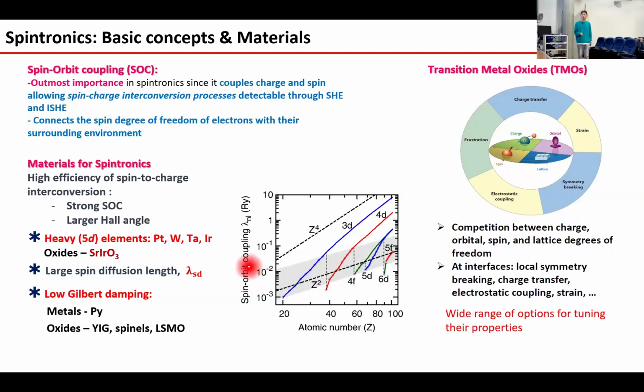In this figure, we show that the spin orbital coupling is strongly dependent on the atomic number, where the 5d elements show a relatively larger atomic number, corresponding to a relatively larger spin orbital coupling. And also another alternative is the oxides, like strontium iridium oxide.